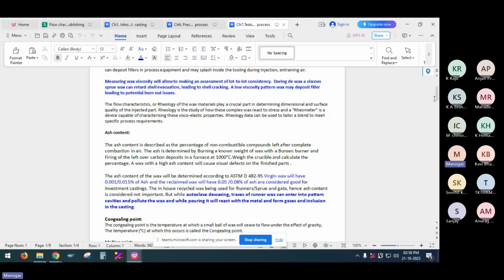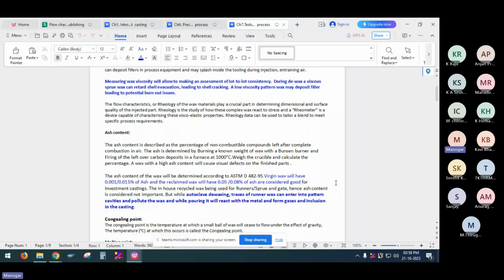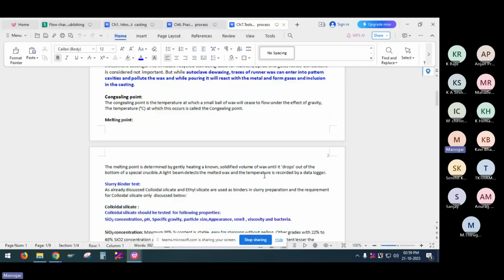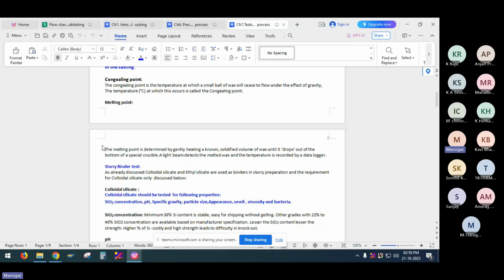For ash content, mostly people follow 0.5% max here, but as per the standard it is 0.001% for new wax, and for reclaimed wax it is 0.05 to 0.08%. Foundry people should consider whether they are able to control this or not. It is better to control within this limit so that you get defect-free castings. Most of the time we get wax defects. When we are using recycled wax, there is a chance that recycled wax is used in runners. When doing autoclave de-waxing, the runner wax can mix with the pattern wax, so care has to be taken, and we should go for fresh wax whenever possible for very accurate or precision parts. The congealing point is for test purposes only. The melting point of the wax is used to fix the melt composition and the melting temperature for the wax part.